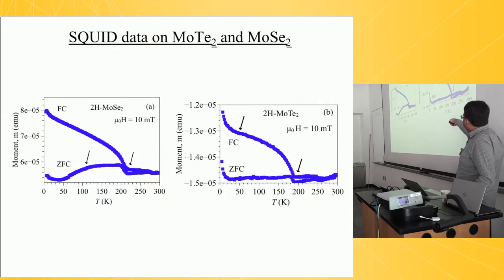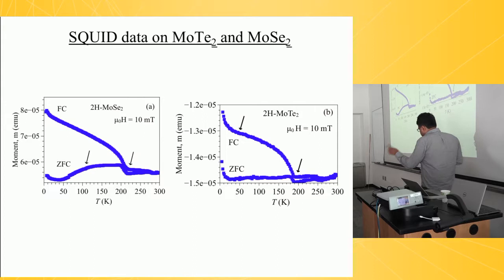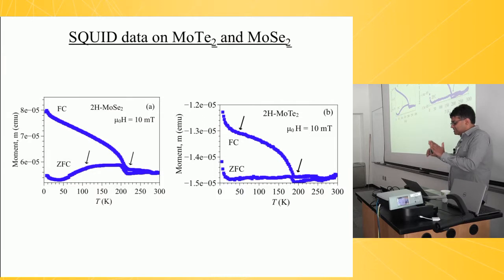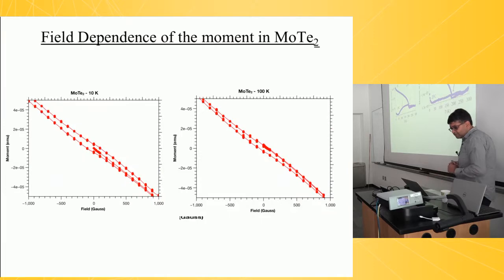And OK, so it's magnetic. So this is moly diselenide. This is moly ditelluride. And you see that in the SQUID, you see the magnetism all the way up to almost 200 Kelvin. And if you go back to the μSR data, this actually corresponds quite well to what you see in the μSR data. There's a temperature below which you have coherent precession, but even above that temperature, you have moments present. And you can tell that by the fact that the signal damps out. So I can get into that in more detail if you want. But these temperature scales make quite a lot of sense with what we see in the muons as well.